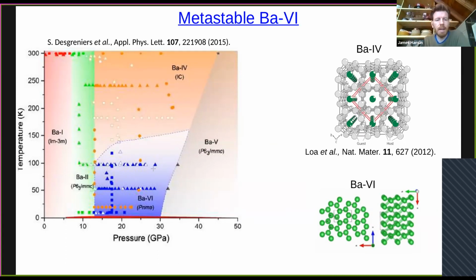But what was found was that there is this very unusual barium 6 phase that only appears at low temperature, but it doesn't appear at low temperature if you cool from high temperature. So for example, if you go to 20 GPa at room temperature and cool down, you do not find superconductivity. Or you do not find this barium 6 phase, excuse me. However, if you first cool down to low temperature at low pressure, say at 5 GPa, and then you start increasing the pressure, you can enter this novel barium 6 phase.